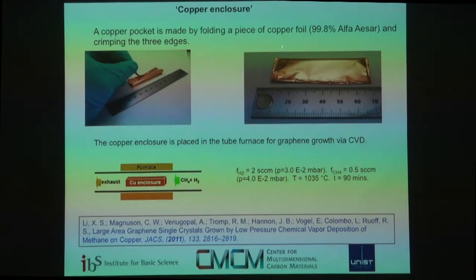And so what Xusong did was he folded over the copper foil. So here's the fold. And there's still some gaps here, and so the methane can get inside and the hydrogen can too, but the gaseous environment on the inside of this pocket is different than on the outside. What happens is on the outside, small grain size, multi-micron grain size graphene coats the outside surface in minutes, but on the inside it doesn't nucleate very fast. And the nucleation density is very small, so the nuclei are very far apart. And if you just wait long enough, those can grow into very large islands and very large single crystals.